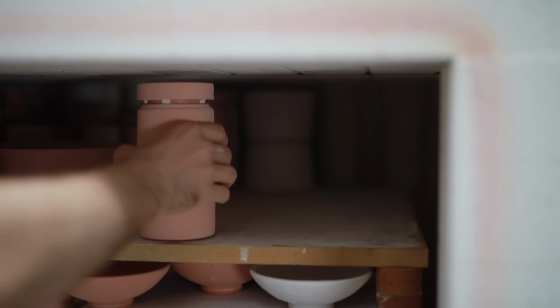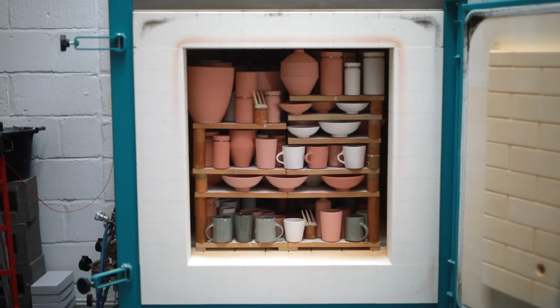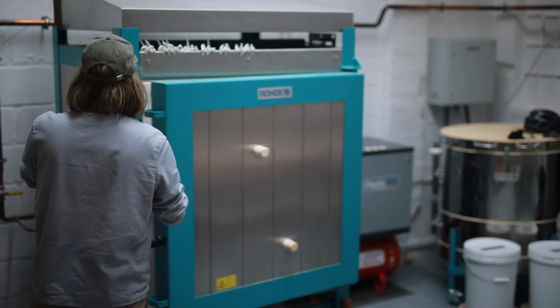There's nothing worse when you forget to do this, and they're positioned at a really awkward angle that's difficult to see. I tend to save the top layer for the most interesting pots. The flames enter the kiln from 4 burners in the bottom, one on each corner, and they're jettisoned up onto these top shelves before being sucked down through the other layers and out the flues in the back bottom of the kiln. So this shelf stays consistently hotter than anywhere else in the kiln, and I think therefore my glazes tend to be a bit more interesting due to the prolonged heat, as opposed to the lower shelf in the kiln, which tends to always under fire just a little bit. Once the kiln's finally packed, I can close it up and leave for the day, ready to come in very early the following morning.